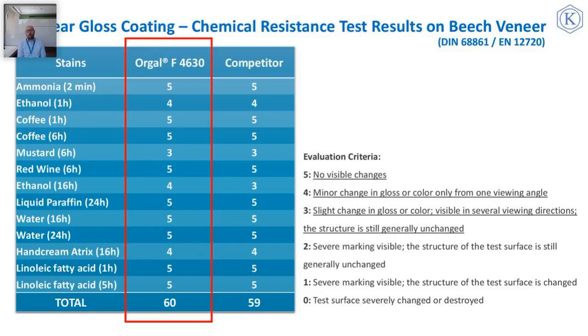Both binders performed almost similar, except for the ethanol resistance after 16 hours. Orgal F4630 has a score of 4, where competitor acrylic is 3. As it will be important for the IKEA test results in my following slides, I will also underline ethanol resistance after 1 hour, which is 4, and water resistance after 16 and 24 hours, which are 5.